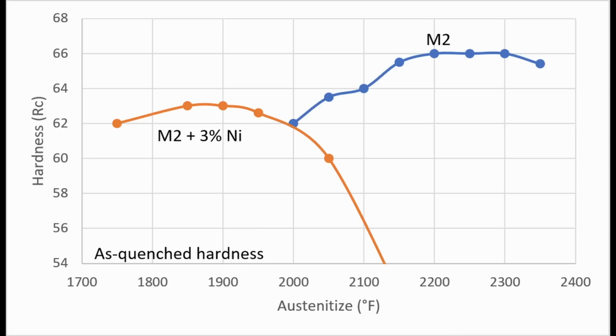So you can see that in this chart I pulled from some old literature data I found, where they looked at an M2 high-speed steel with 3% nickel. And adding the 3% nickel took the M2 from a 66 Rockwell steel down to a 63 Rockwell steel. Now, 3% nickel is more than you need to add, but you might imagine if we want our stainless steels to be able to hit that 64 Rockwell, and then we add 1.5% nickel to it, that might become a 62 Rockwell steel, which could be undesirable.